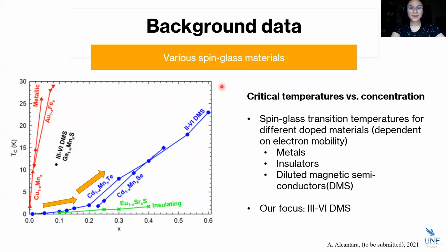So getting right into it, this is an evolving plot of the transition temperatures as a function of their doping levels. And because the spin glass is dependent on electron mobility, you can see that the metals have a quick rise in their transition temperatures with very small levels of doping due to the high levels of conduction in metals. And this is no good for our study because there's so many electrons in the system that we won't really be able to pinpoint what's going on.